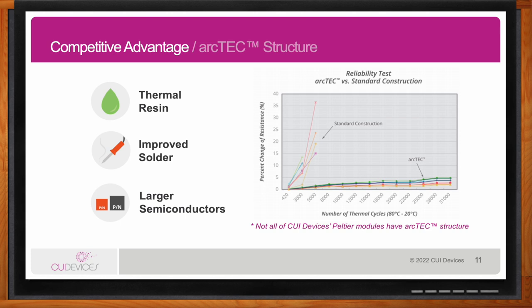However, if you look at the lines on the lower portion of the graph, these are the products that have the arcTEC structure that we tested, and we see very minimal performance degradation at the same number of thermal cycles. In fact, we see little performance degradation well beyond and up to 30,000 cycles. So this graph highlights the main benefit of the arcTEC structure.